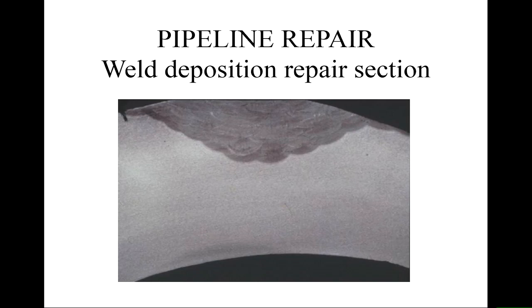So here's a weld deposition repair. This one had lots of passes in it. There was about 4 to 5 passes because it was quite a deep repair. It just depends on how much corrosion there's been. For very old assets where you're approaching the limiting thickness for the pipe at the bottom of the corrosion pit, this is a way of refurbishing them and getting them back up to a much higher standard. And if you've qualified the welding procedure properly, you can effectively reset the thickness in your calculations. Not always possible, depends on the standards, the codes you're working to, but in many cases it's as good as you're going to get.